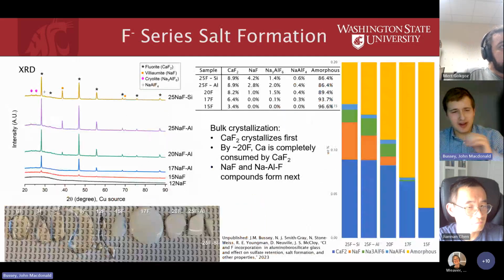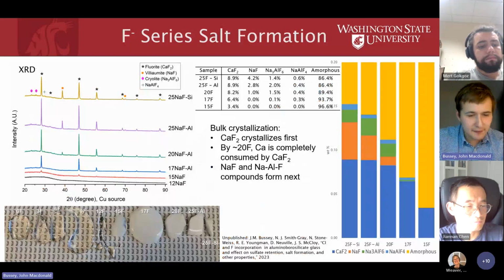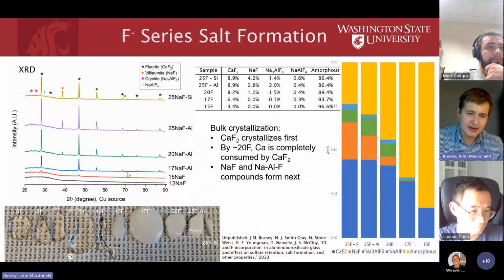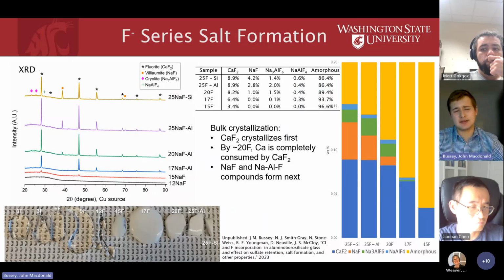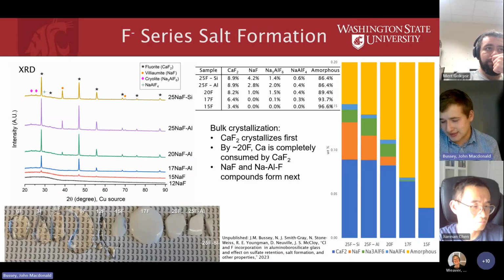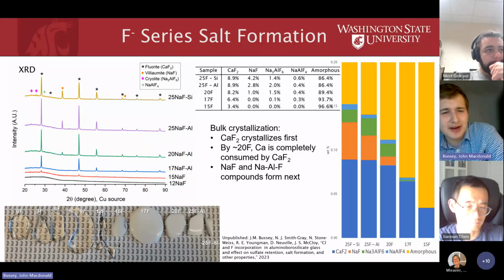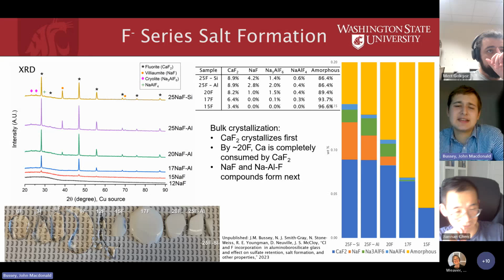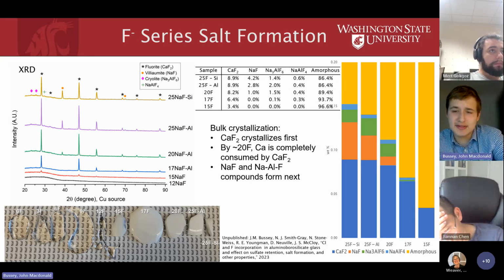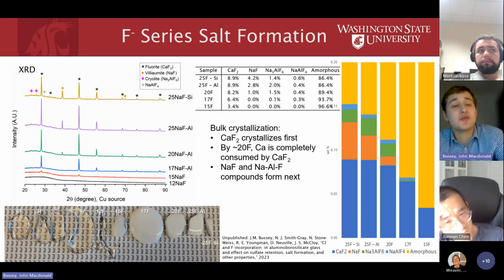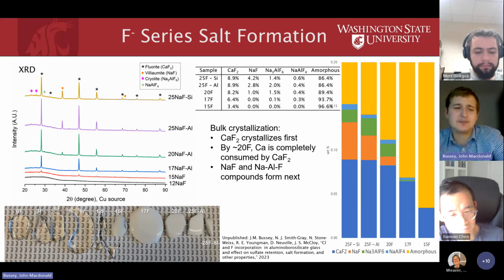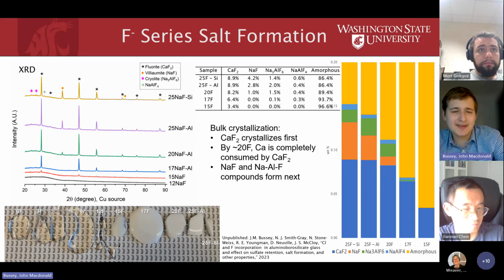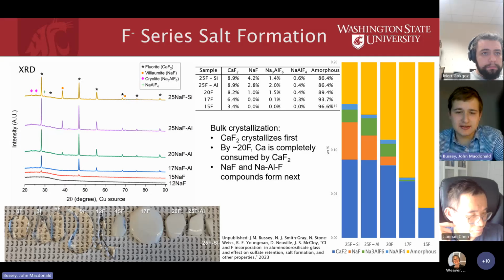So for the fluorine glasses, these were much more complex. As you can see on the bottom, as we add fluorine, around 15 weight percent fluorine, the glasses turned opaque and then got very white. They looked like porcelain maybe. Looking at X-ray diffraction, it indicates that a significant amount of crystals start to form at the highest fluorine loading. Calcium fluoride crystallized first, and then sodium fluoride and sodium aluminofluorides crystallized later, indicating that calcium fluoride is probably the most prevalent phase to form.